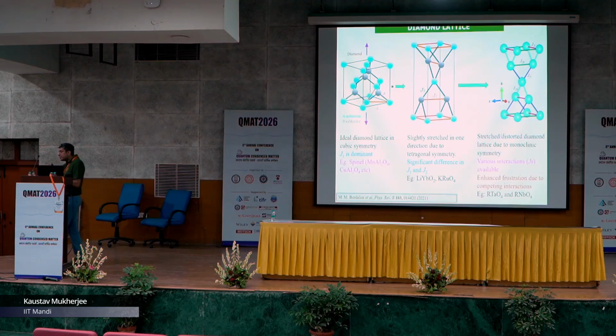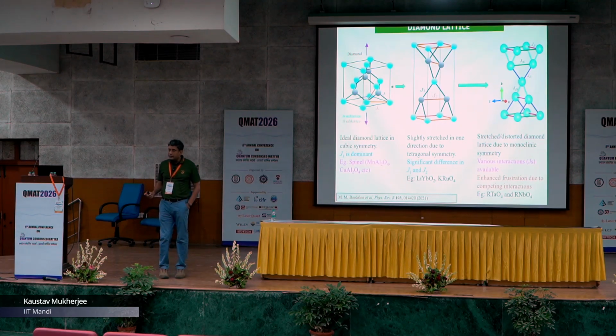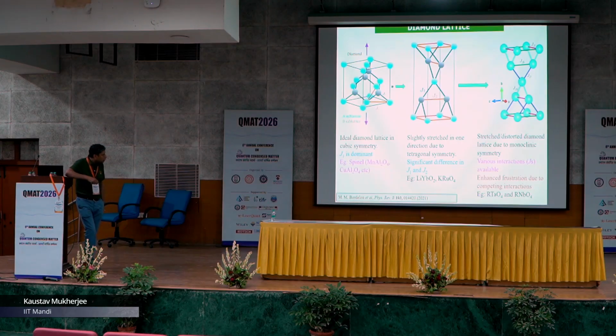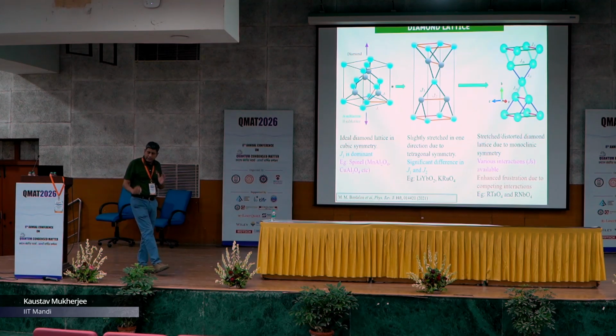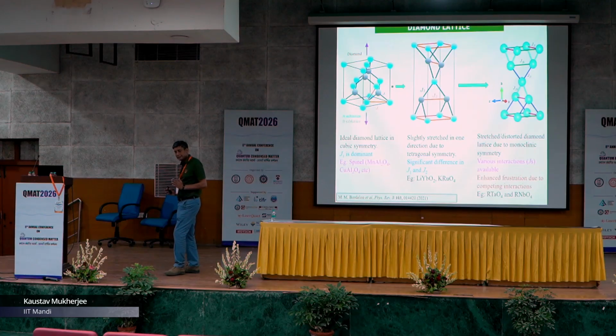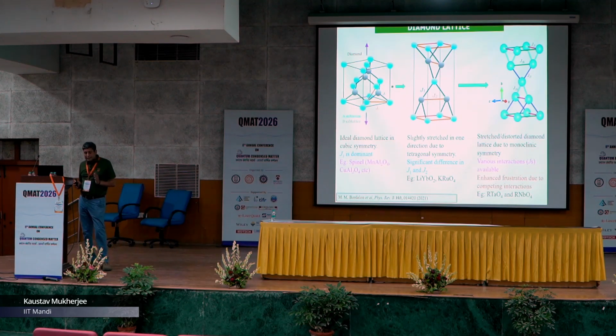Now further, if the symmetry is reduced from cubic to monoclinic, then due to this reduction in symmetry, in J1 we can have a long bond length and a short bond length, and in J2 we can also have a long bond length and a short bond length. So due to this reduction in symmetry, the diamond lattice becomes stretched or distorted in the monoclinic symmetry. Compared to the other two systems, there are various J interactions present which are of comparable strength, and due to this there is an enhanced frustration effect in this system. Such stretched lattice geometries have been seen in some members of the rare earth tantalate or rare earth niobate series.